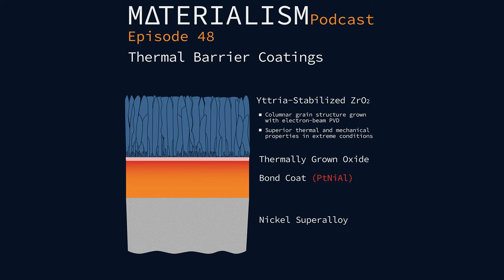The plates are parallel to the surface of the metal, whereas you get a completely different structure with EB-PVD, the electron beam structures. The first time I saw them, I remember thinking that I was looking at a feather or something like a wing, because these things are vertical, they're columnar, and the columns aren't like solid shafts. They're these feather-looking structures that are filled with porosity, obviously, inside of them, and also between the ridges between columns. Now, there's some big benefits to this approach, EB-PVD.